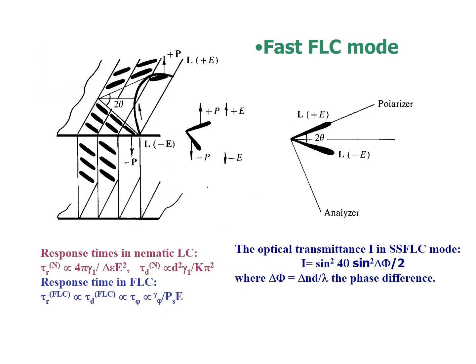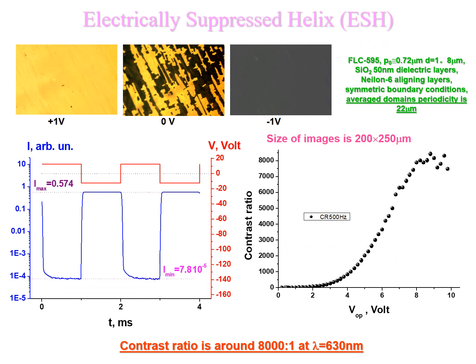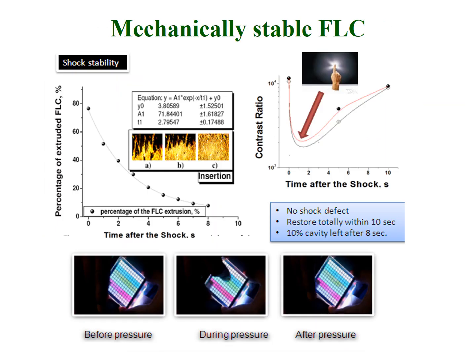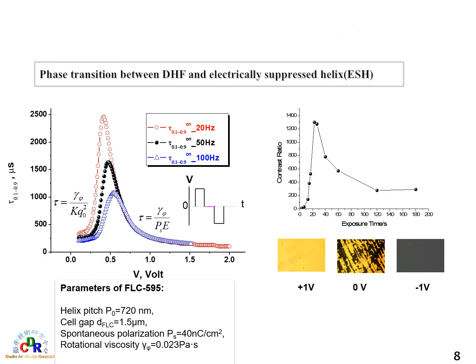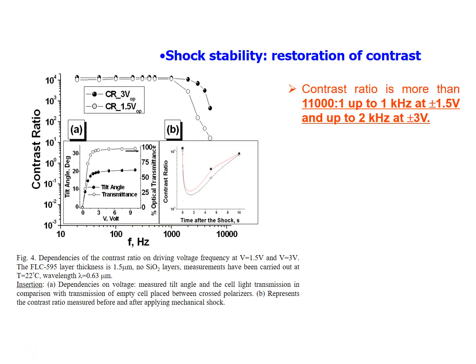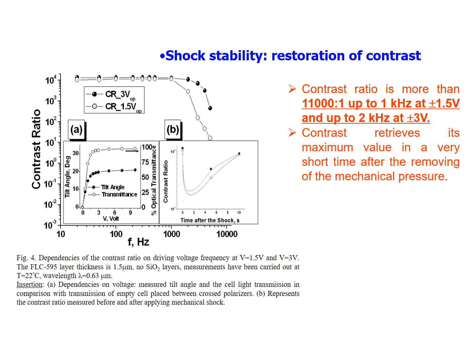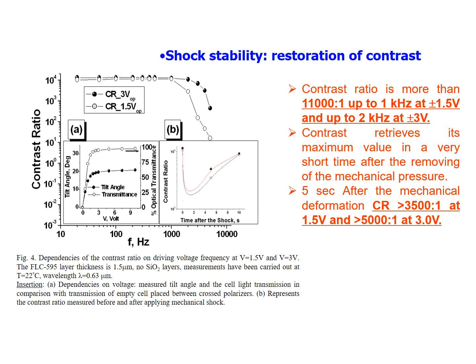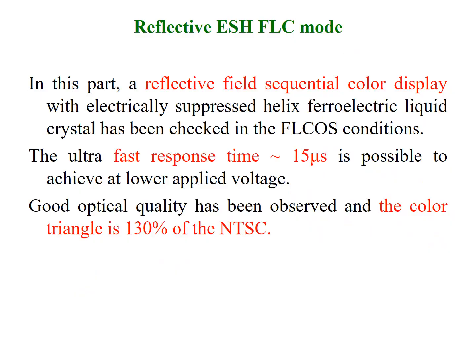So ferroelectric liquid crystal is much faster because this is a linear electro-optical mode. It can be very, very fast, and it can have an extremely high contrast ratio. And also the problem of mechanical stability is completely solved. So here you will see the typical parameters of ferroelectric liquid crystal electro-optical modes, which we call the electrically suppressed helix mode. For this mode, we have an extremely high contrast ratio. We have also very good contrast ratio, and we have shock-free displays.